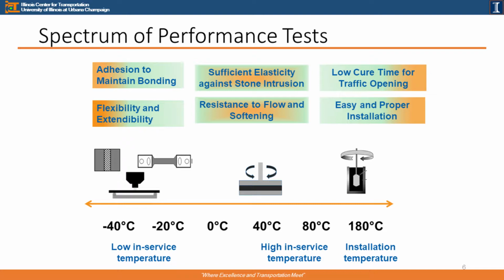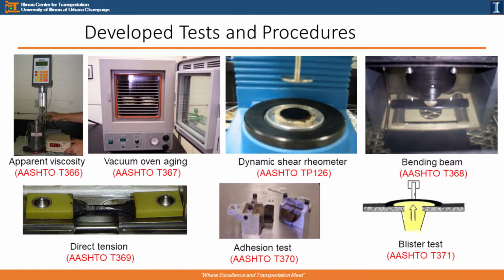And then we have to consider the characteristics at high temperature and low temperature. So for the high temperature, they consider sufficient elasticity against stone intrusion, and also they considered resistance to flow and softening. At the low temperature, they consider adhesion to maintain bonding, and at the same time flexibility and extendability. And then they utilize existing equipment, or they developed a couple of new pieces of equipment for sealant. Actually, crack sealant they call. So these are the developed tests and procedures.